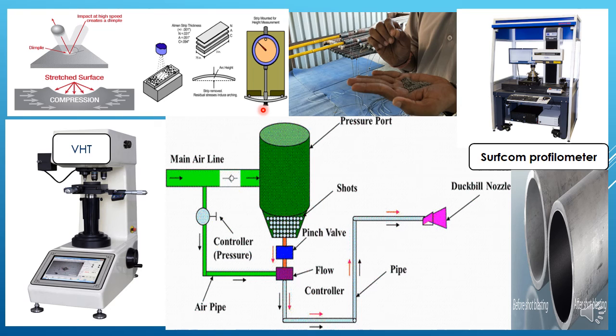Besides this, we can carry out several tests like the Vickers hardness test for measuring hardness. The hardness can be increased by more than 30%, and there is a surface profilometer. It measures the surface roughness, and there is a rotating bending machine as well for measuring the fatigue strength. Fatigue strength can be increased by 25 to 35%. Like this, we can increase the life as well as the surface compressive stress. Thank you for listening.